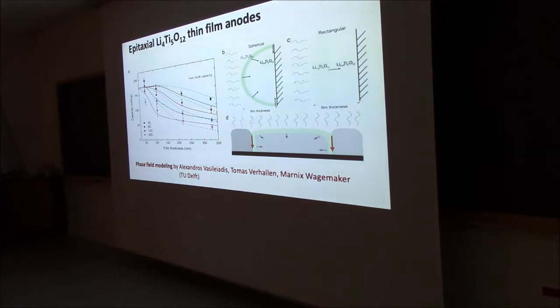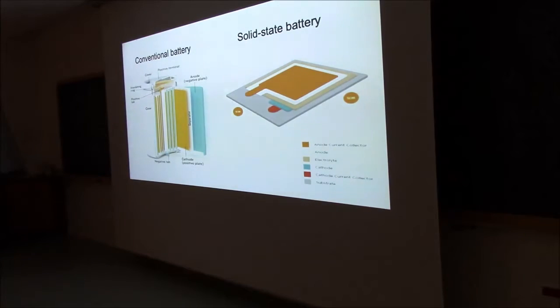Because very often we get numbers which are not even close to the theoretical what you would get. Is this because of just the way that you make it? So we collaborated with colleagues from Delft, and they did phase field modeling to look into how lithium would move throughout a material, let's say only from the top, this rectangular orientation. That was not sufficient to explain everything. But if you combine it with a spherical contribution, which means that you have grain boundaries where the lithium moves in fast and then moves in sideways, then you can fit this data in a pretty reasonable way and get all the trends that we see there. So that was, I think, a nice confirmation. This was published a few months ago.